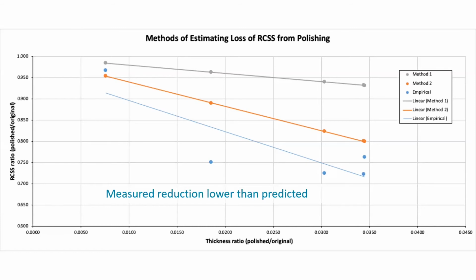A few notes here: this indicated to us that we really need to measure these things on a case-by-case basis, because we don't know. Oftentimes, we found that the client or the drawings or otherwise don't always correctly identify what glass is actually on the building. And two, we have no way of knowing what the RCSS is when it's heat treated until we actually go and measure it, because all the manufacturer has to do is make sure they exceed the minimum. So we've come to the conclusion that we really have to go out there and measure these things on a case-by-case basis. Maybe sometime in the future we'll get a sophisticated enough model, but we're still likely going to have to figure out what the RCSS is initially, even with a more sophisticated model.